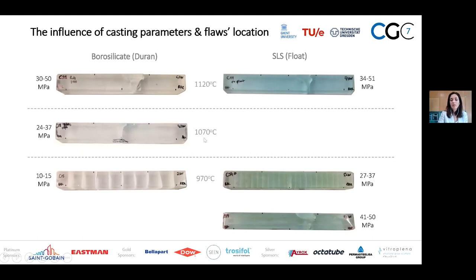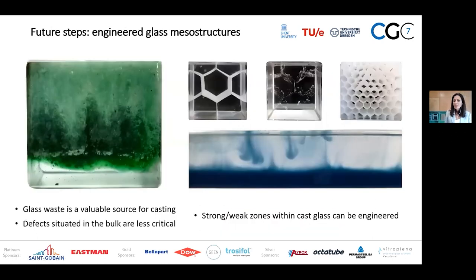Also notice that only 50 degrees of difference can have a big impact on the strength. And these two beams over here look exactly the same. The second one, due to this very subtle defect, due to the higher casting viscosity, failed at a lower strength. So actually what we understand from this study is that yes, glass is a very valuable resource, and it leads to a great variety of mechanical properties, but also very interesting aesthetical expressions.